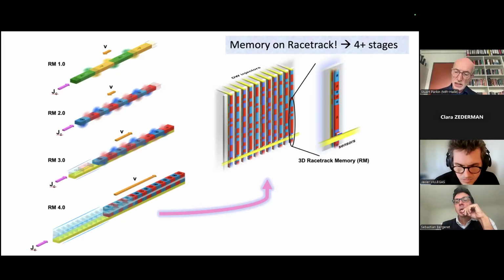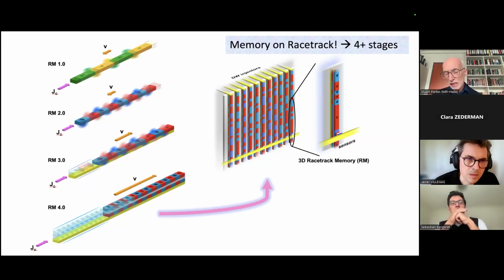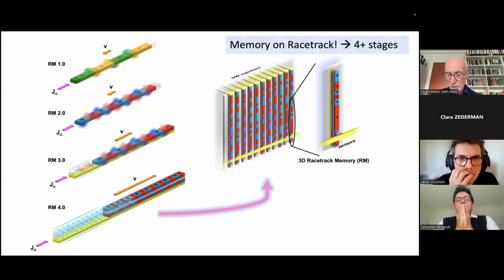And in these cases, we accidentally discovered that the velocity of the domain walls is significantly increased from 3.0. In fact, here, the domain walls we demonstrated could move at speeds of up to 1 kilometer per second. So this is extremely interesting. These are very high speeds, 1 kilometer per second for the same current density as in 3.0. And it turns out there's an additional, what we call a giant exchange torque, which derives from the very large antiferromagnetic coupling field between the upper and lower racetrack.